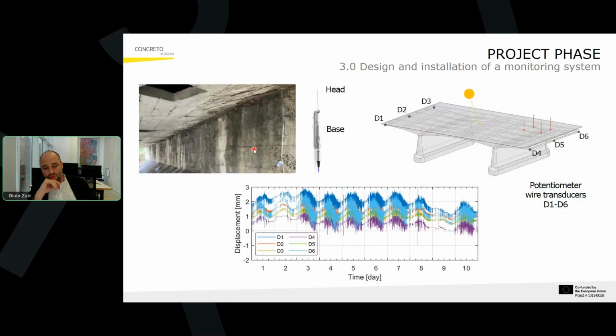This is an example of one reading. It's about 10 days. Then I will show you that we observed the bridge for quite a larger time. But you see that if we observe the vertical displacements, channels 1 to 6 at the end of the deck, we have a behavior characterized by a slow fluctuation, which is mostly associated with the thermal loads, so the presence of solar radiation, plus a series of peaks.